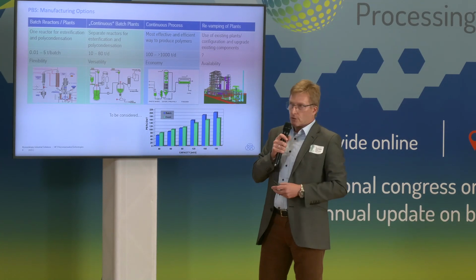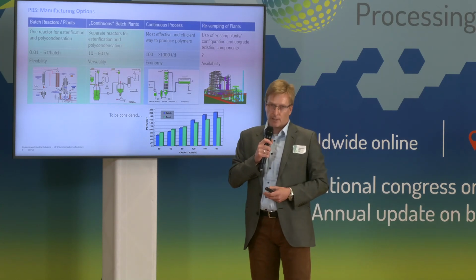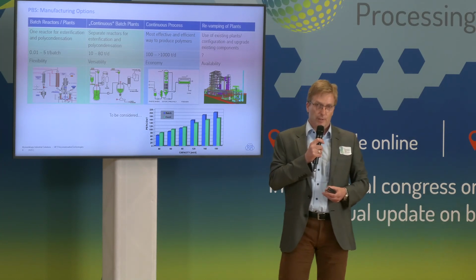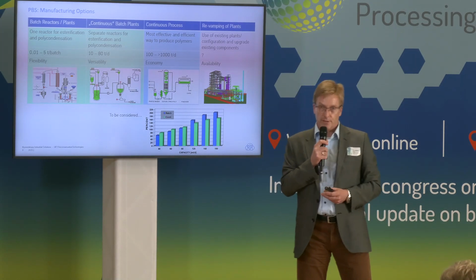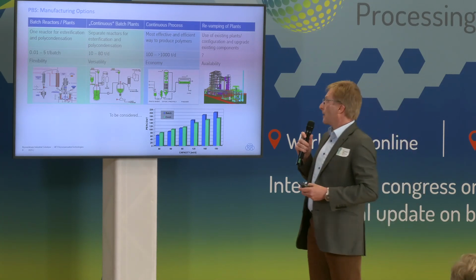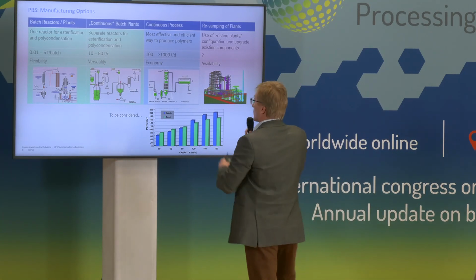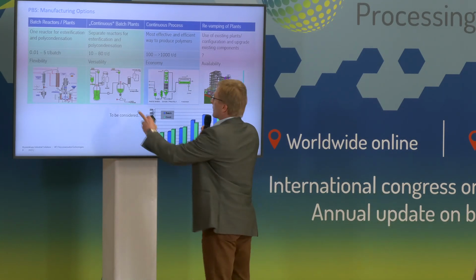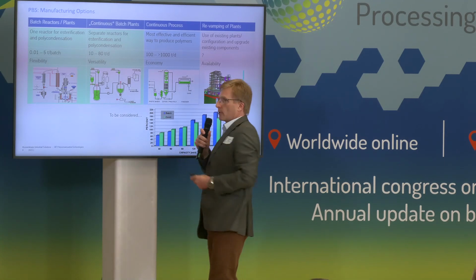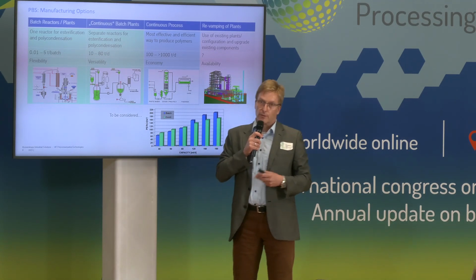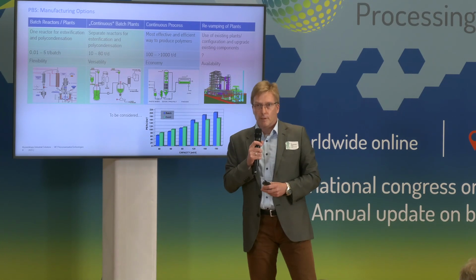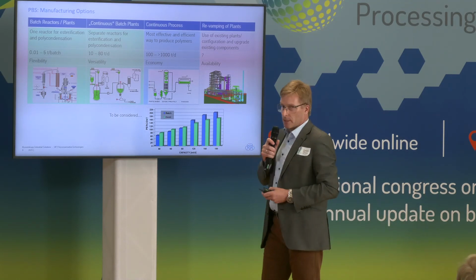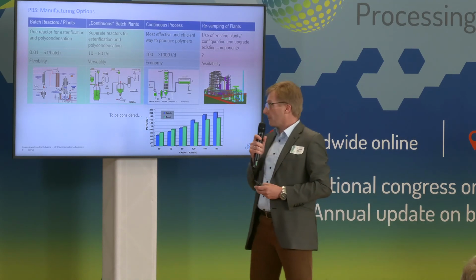The benefit of such a simple device is the high flexibility. You can use it for making PBS, but you can more or less make every polycondensate in a reactor like this. The next step would be a continuous batch plant where you have an esterification reactor and a polycondensation reactor separated. This typically would be a plant setup for capacities between 10 and 80 tons per day.